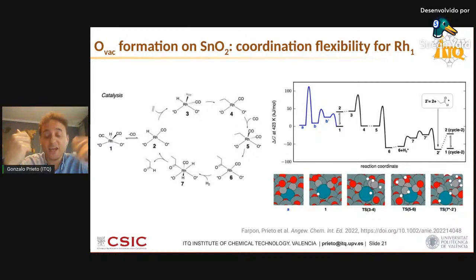This is a dicarbonyl, but it's actually a hydride dicarbonyl, as we could confirm with IR spectroscopy. Only this species, and not the hydride-free dicarbonyl, matches the vibrational information we were getting after in situ reaction in an FTIR cell. This is a rhodium with an unusually high coordination flexibility, thanks to this loss of oxygen ligands. And it's so coordination-wise flexible that it can engage quite easily in a conventional Heck-Breslow type of reaction mechanism. That's a mechanism which is more typical for molecular complexes in solution.